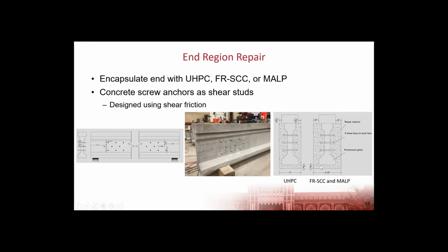For the FR-SCC and the MALP concrete, which had a lower strength, so I should say the UHPC is about an 18,000 PSI material, the FR-SCC is about 6,000 PSI, and the MALP concrete is about 12,000 PSI. So for those two lower strength materials, we increased the thickness of that section out to 3 inches on the bottom flange, and again, constant rectangular section.